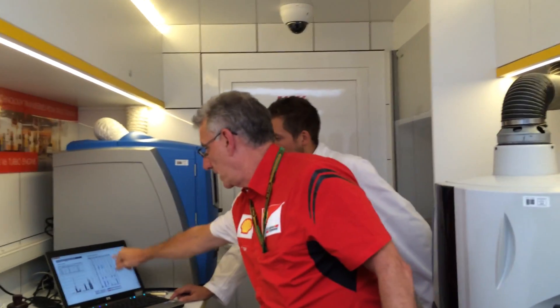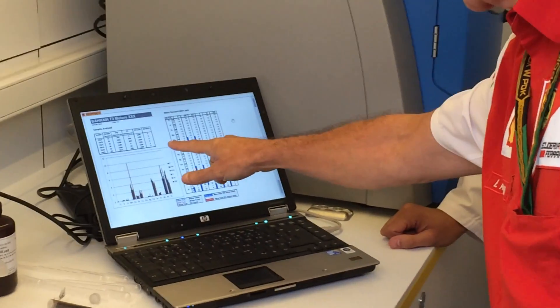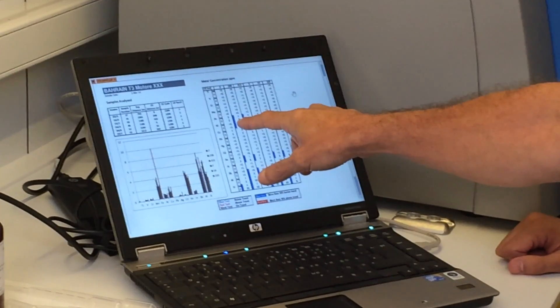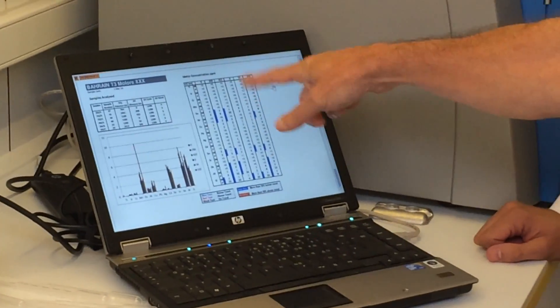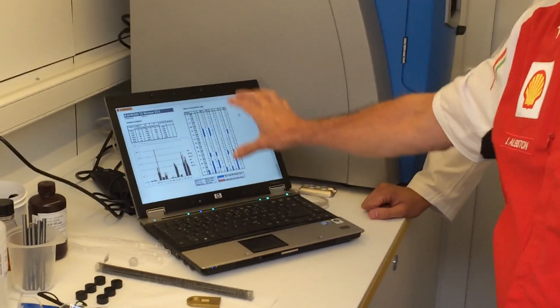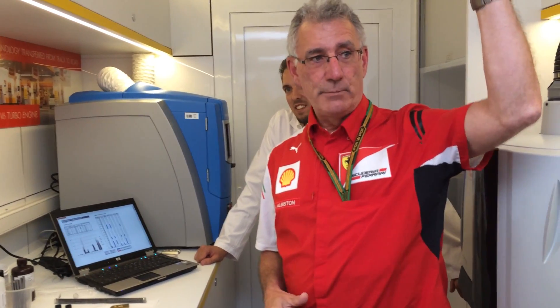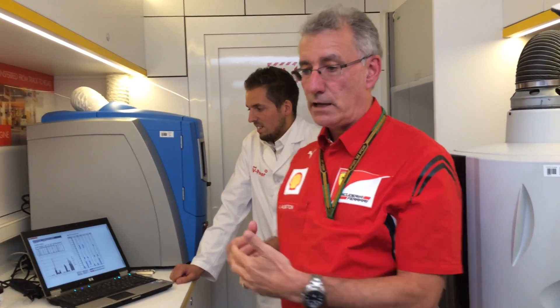These are the printouts we get — there'll be a predicted value. For instance, iron after 298 kilometres: we predicted 8 parts per million of iron, and we actually got 3 — so that's blue, which is good. Blue is always good; red is bad. You can see there's no red on there, which is quite good. Within 2 minutes of the car coming back into the garage, the Ferrari engineers upstairs — we go up some spiral stairs — have the results and know whether that engine is wearing abnormally or normally.